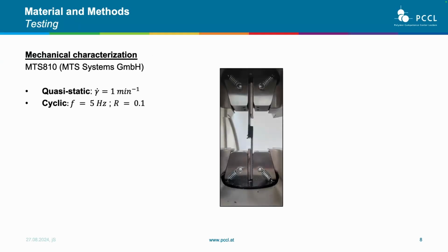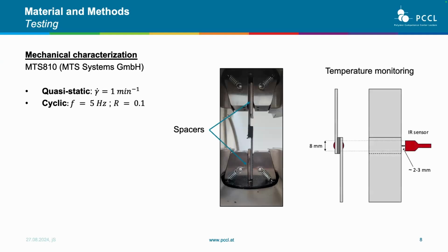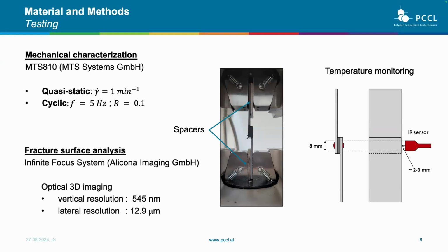The tests were performed with an MTS system. You can see both quasi-static and cyclic loading. Especially, I would like to focus on the 5 Hertz that was chosen. All the parameters were chosen after some preliminary tests. We used some spacers in the clamping to maintain the alignment during the testing. And we monitored the temperature with an IR sensor, because 5 Hertz can already be a relevant frequency for causing heat buildup in the elastomers. Then the fracture surfaces were analyzed with an Infinite Focus system by Alicona. This provides a 3D overview of the fracture surface, and afterwards you will see why we chose this one and not a typical microscope.